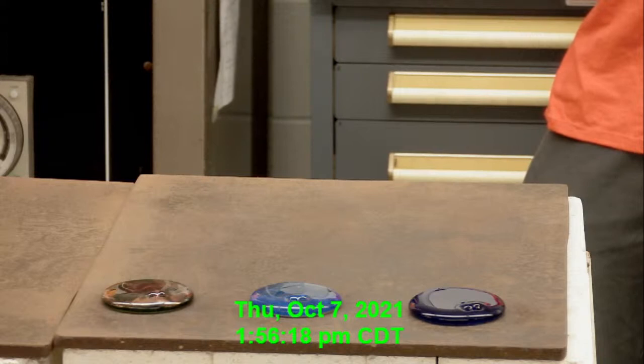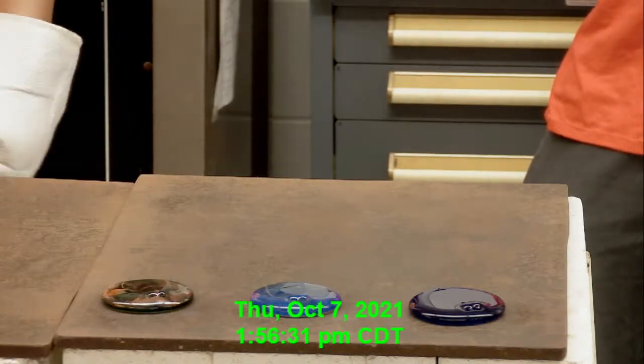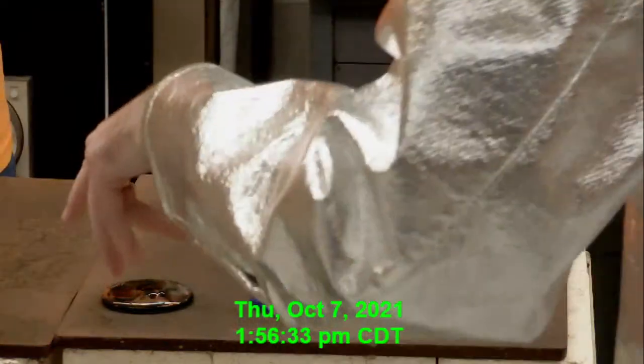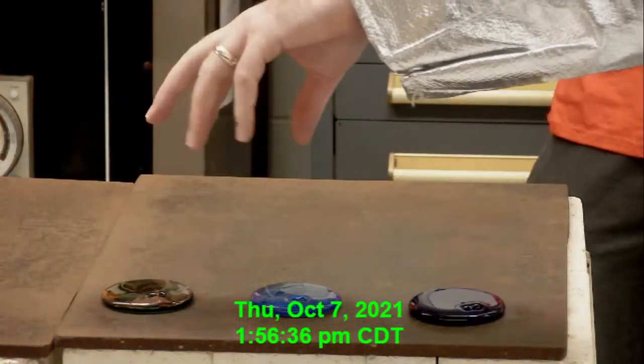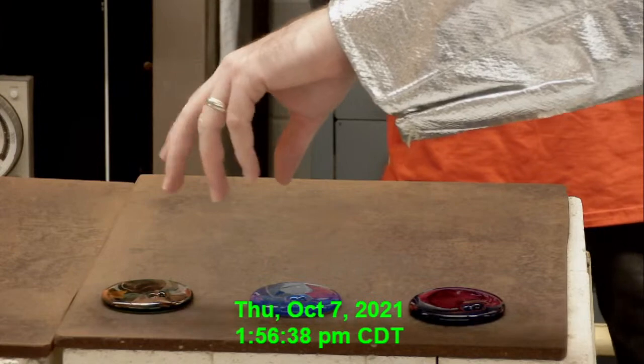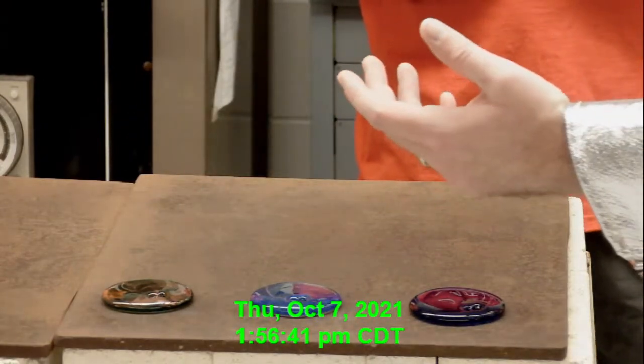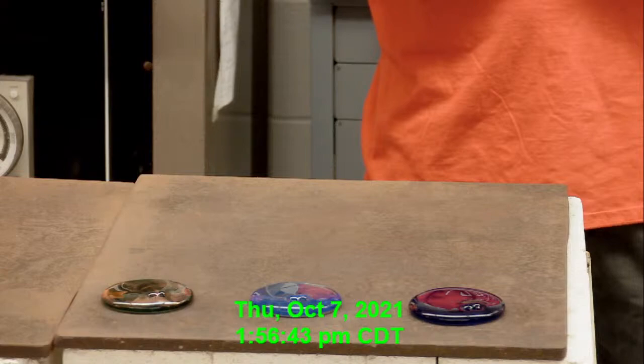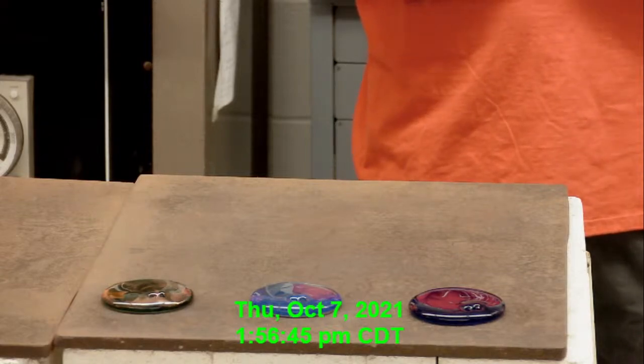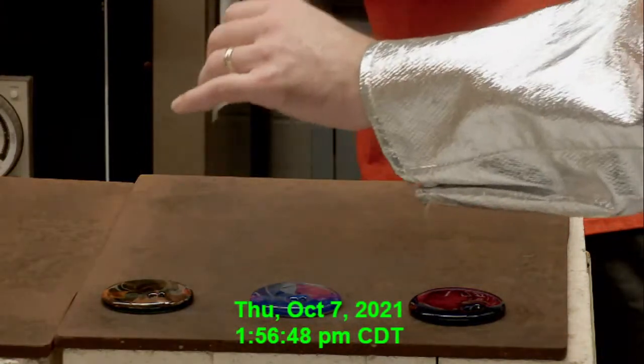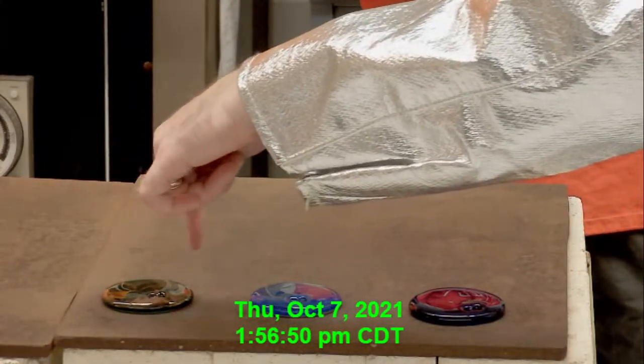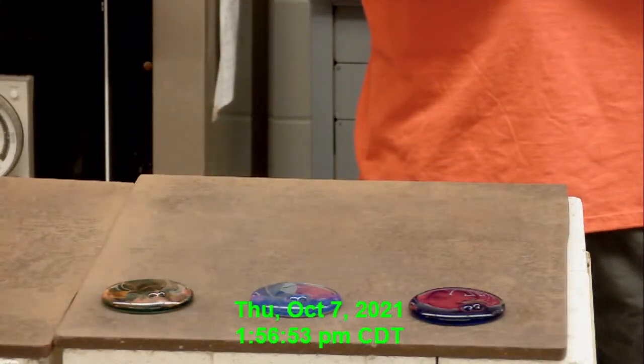And I'll clean up these crucibles later, so we could, in theory, chip off that glass so it's not like a bee stinger that's going to get you. But yeah, this is kind of cool. I can see, and you'll be able to see later, there's a mottled, coppery, like bands of sort of metallic-looking copper on top, and that's due to carbon monoxide in the flame before it completely combusts. It has pulled some oxygen out of the oxide, leaving this copper appearance on top of the glass. So that's kind of neat.